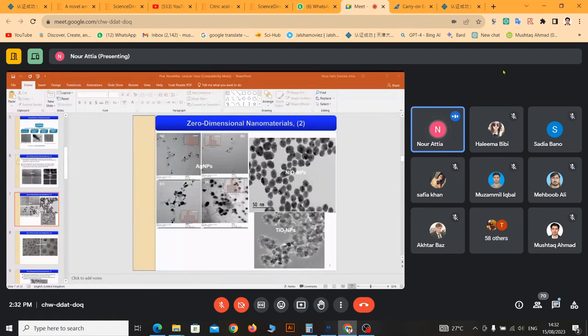Many people working with nanomaterials use very expensive material, but the yield and the application will not be good because they use the material as it is. You have to individualize, because without individualization of your nanoparticles, you will not harness the value of that material. It's very important, because nanoscale materials have a higher surface area. For example, titanium dioxide in macro scale has a surface area of 10 or 20 meters square per gram. But titanium dioxide nanoparticles may have 300 or 400 meters square per gram. Then they will aggregate together, and they come together by different kinds of interactions, dipole-dipole interactions, many interactions. So it will be aggregated.